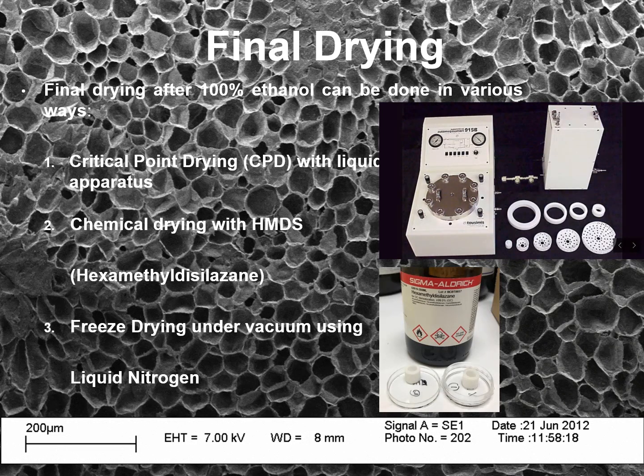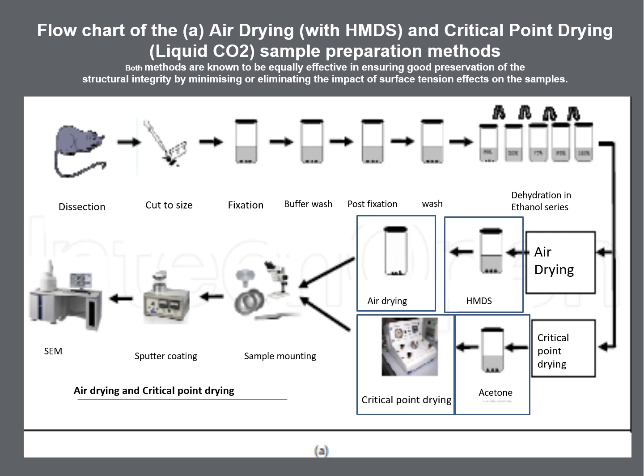Final drying process. Final drying after 100% ethanol can be done in various ways. Number one, you can try critical point drying with liquid CO2 in a critical point drying apparatus. Or you can use the chemical drying option with HMDS, or the freeze drying option under vacuum using liquid nitrogen. Here I present a flow chart of air drying with HMDS and critical point drying with liquid CO2. Both methods are known to be equally effective in ensuring good preservation of structural integrity by minimizing or eliminating the impact of surface tension effects in the sample.